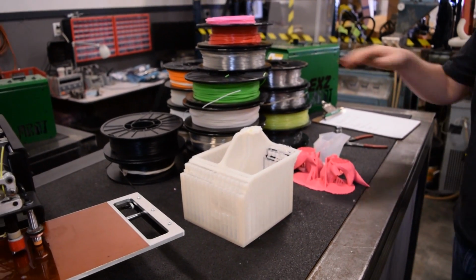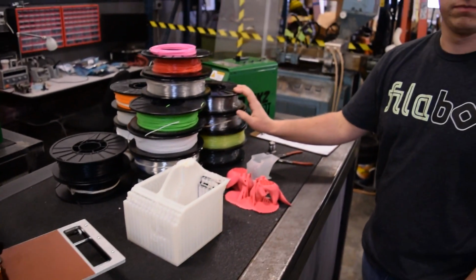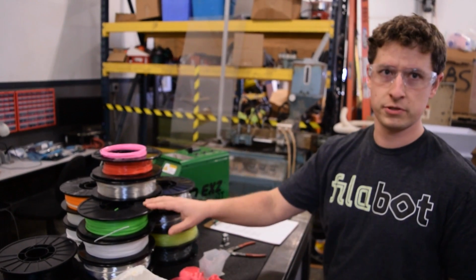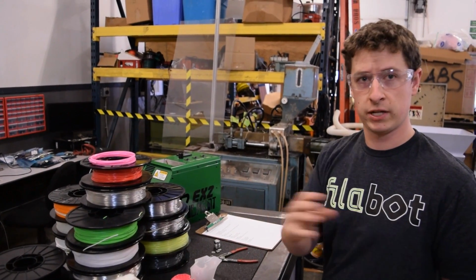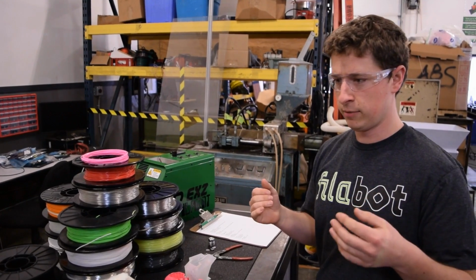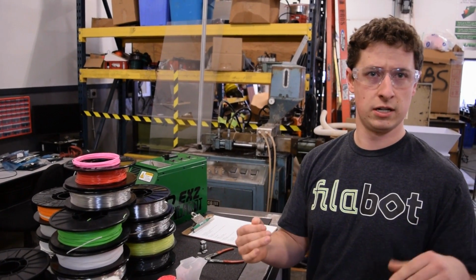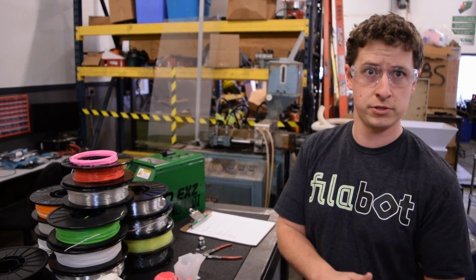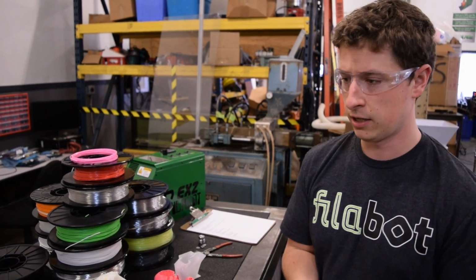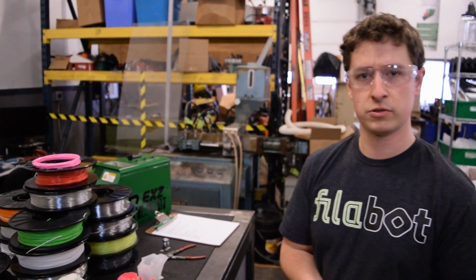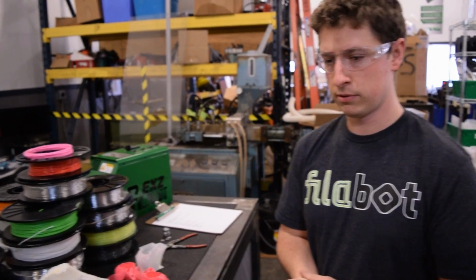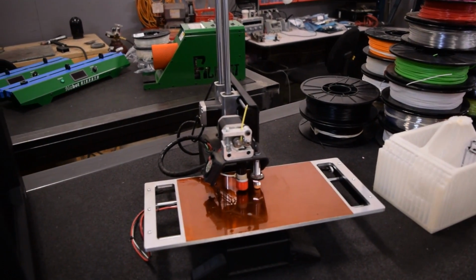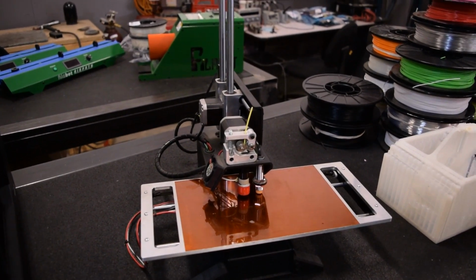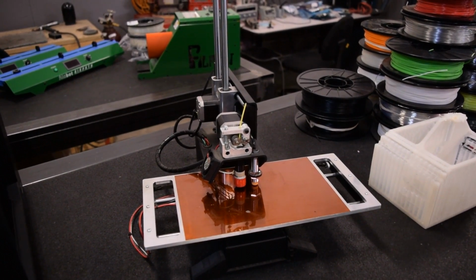For materials you buy offline or from other manufacturers of filaments, they'll have the temperatures worked out. In our case, when we're playing with different polymers, you have to test the different ranges of hot end temperatures and build plate temperatures to find that good temperature to where the filament isn't going to slip, where the drive system isn't going to be unable to push it anymore. Melt flow, so that kind of ties into the temperatures.